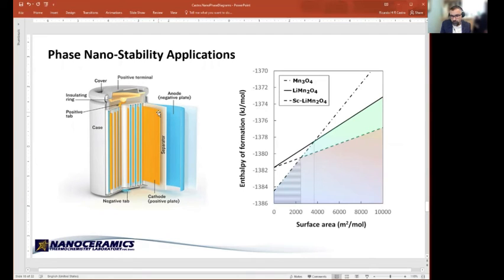Basically, what we're showing here is that one thing we can do to help the community is provide the phase stability diagram at the nanoscale. What happens with the LiMn2O4 is that it can actually collapse into Mn3O4 in the system. And from what we realize, similar to the system we just discussed, Mn3O4 is more stable when you have large grains in the microscale.